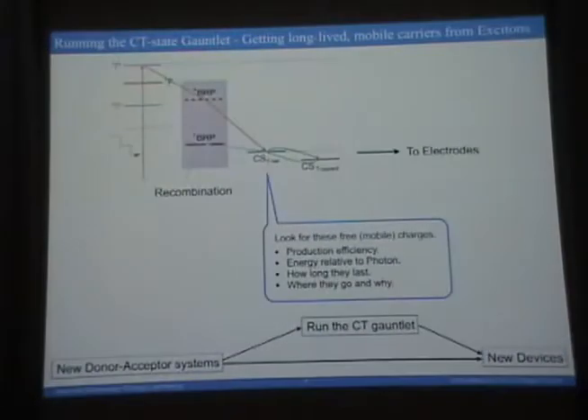Okay. In this process, what you can understand is that the key components are getting through this point here. Excitons into free carriers and get them out from the electrodes. The problem is that you have competing processes. Those free carriers can come back to the interface where I guess they'll form this bound radical pair or charge transfer state and then possibly recombine. That's the only recombination pathway they have, is to go back to that interface and recombine.